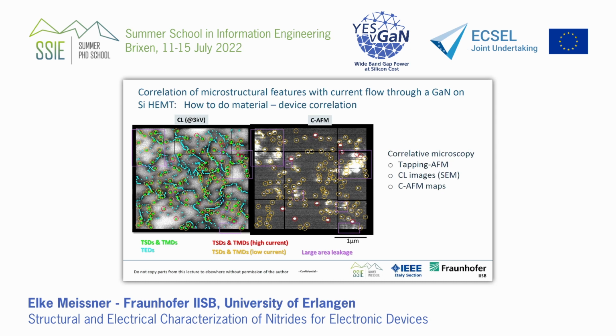This correlation scheme is quite complicated because now you have to put everything together. Before processing, after processing of a device, observing the epitaxial layers, observing the whole epitaxial stack, observing the substrate. Now put everything together with all microscopic means that you can achieve and say, okay, they make sense. Luminescence imaging, conductive AFM, tapping AFM, and of course we observe the material plainly in SEM. Now you get this picture and you can overlay it. Luminescence shows us the dark spots at any place where there are dislocations. These black ones. We put the blue points.